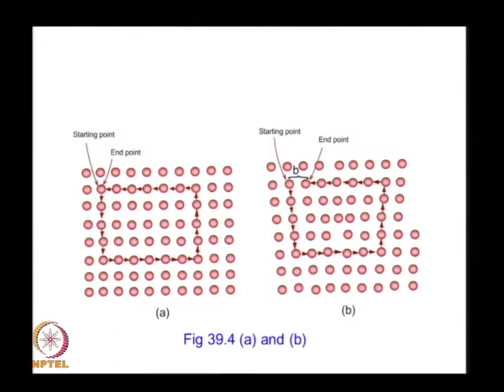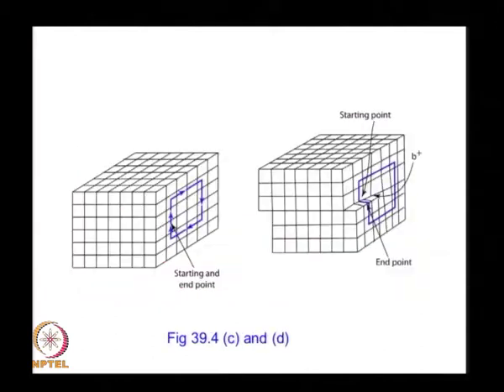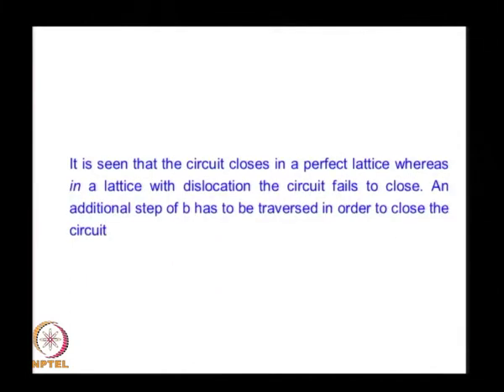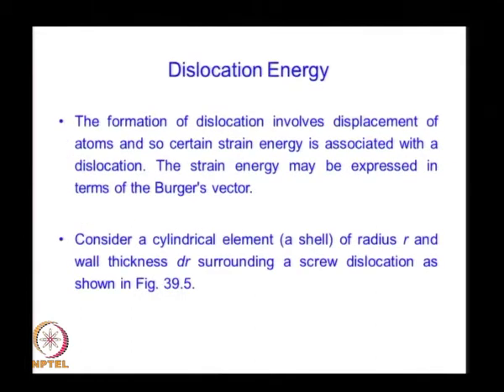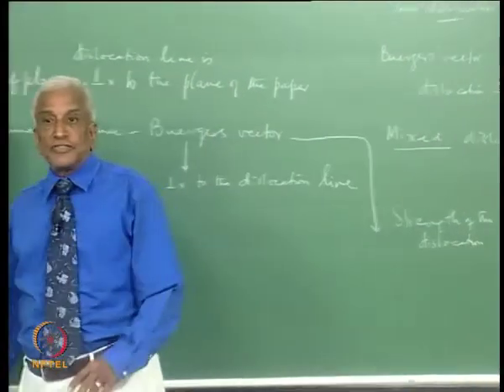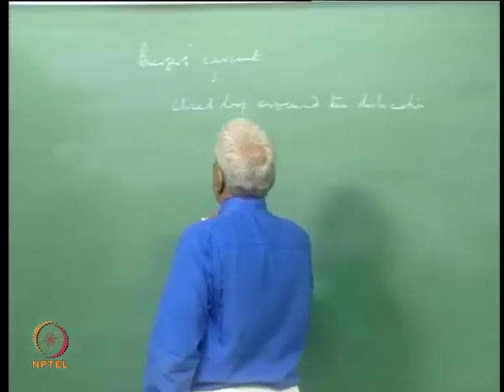and in figure 39.4a you see a perfect lattice without a dislocation where the Burgers circuit comes back and closes, whereas in figure B of the same, you have a dislocation. So, there is a slip which has occurred, and therefore, the Burgers circuit is not closed, and this is in connection with a screw dislocation. The same situation is shown for an edge dislocation in 39.4 C and D. So, you can see that the circuit closes in a perfect lattice, whereas in a lattice with dislocation the circuit does not close. An additional step of b equal to the Burgers vector has to be traversed in order that the circuit is closed. We said that the Burgers vector is a measure of the strength of the dislocation. So, we will consider dislocation energy in order to see this.